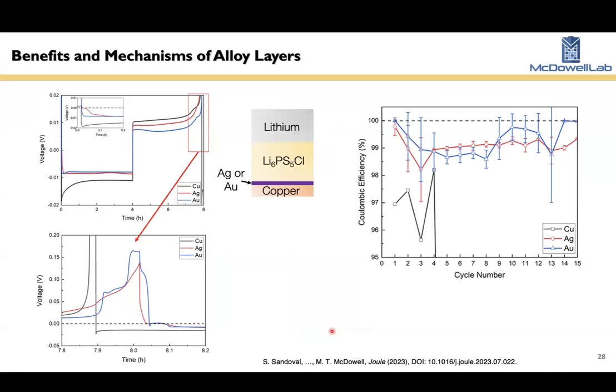One of the things we've investigated to try to solve this problem is the benefits or mechanisms of alloy layers. So this is a similar scenario here. If you look at this middle schematic, we're now testing a half cell with a copper current collector. Instead of just bare copper, we're depositing 100 nanometers of either silver or gold. So there's been a lot of work in literature focused on silver in particular, showing that in various contexts, either in composite electrodes or other types of interfaces, it can behave pretty well. And what we wanted to do here was understand why this is happening.